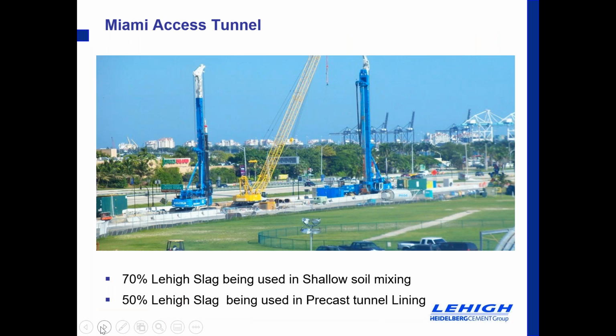Slag was employed on this project in two ways. One, in the geotechnical side, where we use 70% slag in shallow soil mixing. And also, interestingly enough, we used 50% slag in the precast tunnel lining, concrete precast tunnel lining. And I know there'll be other discussions about precast and so forth, so I don't want to get into that too much. But I will say this was an interesting use of slag cement in the precast tunnel lining, in that there was a 150-year life cycle that we had to try to identify for the precast, and the winning mix used 50% slag to achieve that, and part of that being because of the low permeability that we could then factor into the durability analysis. But today we want to talk about more of the geo side, the 70% slag and the shallow soil mixing. Next, please.